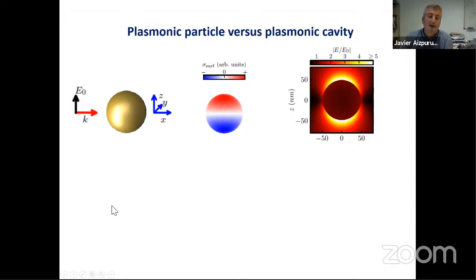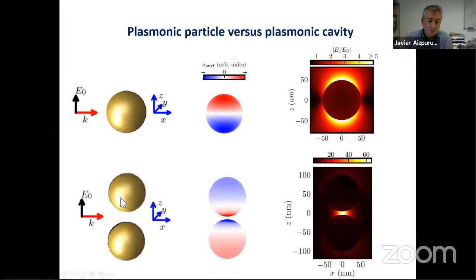When you do that, and this is what I show you here below, you have two metallic nanoparticles, and the resonator at the top and the resonator at the bottom interact via Coulomb interaction, because remember that these are oscillating dipoles, oscillating charges. And if you put the bottom of this particle and the top of this particle closer together, the oscillating charges interact via Coulomb. As a result, they produce a hybridized solution, a hybridized plasma oscillation, a hybridized resonator mode that traps light even further.